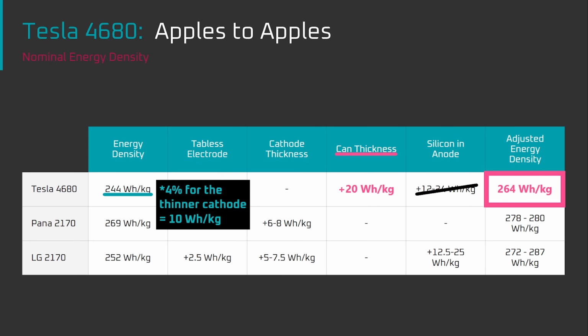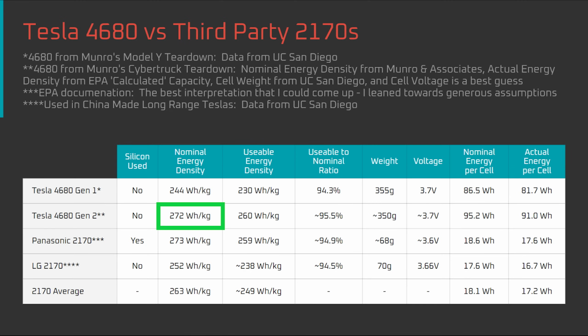If we add that to the 264 watt-hour per kilogram hypothetical cell energy density from the thinner cell can, that would be a total hypothetical energy density of 274 watt-hours per kilogram, which is within 2 watt-hours per kilogram of the energy density that Monroe and Associates measured.